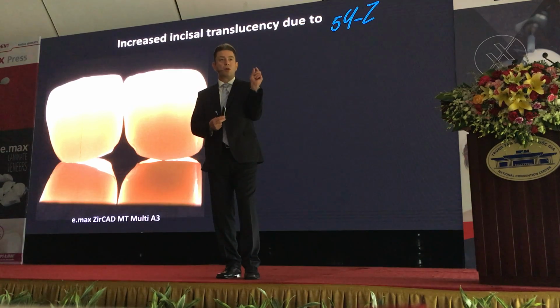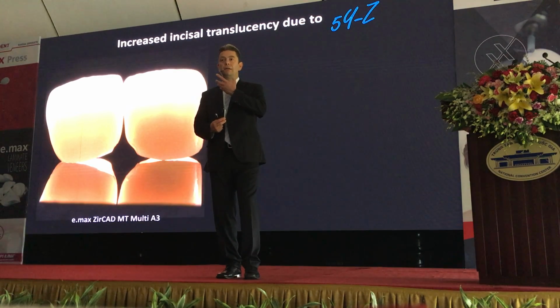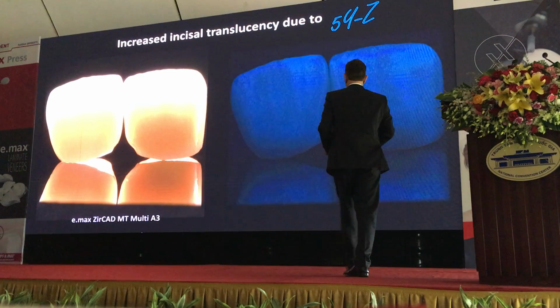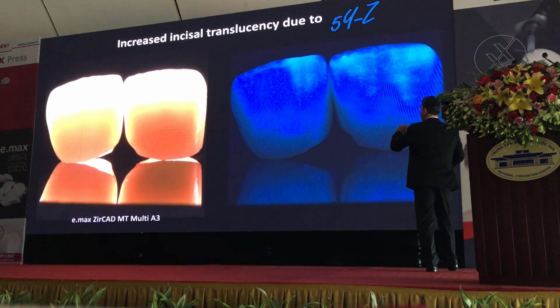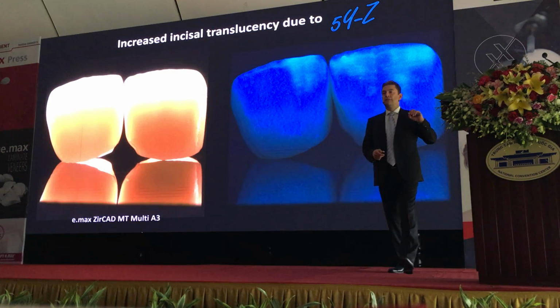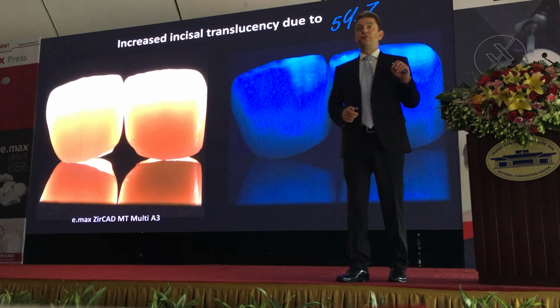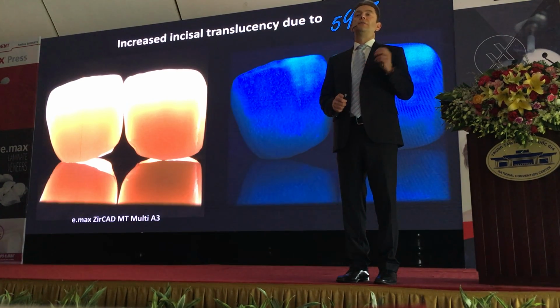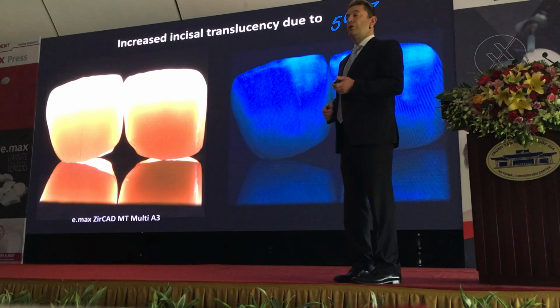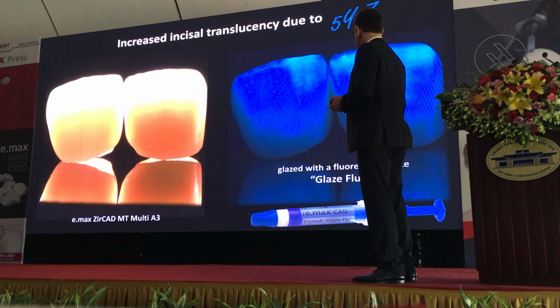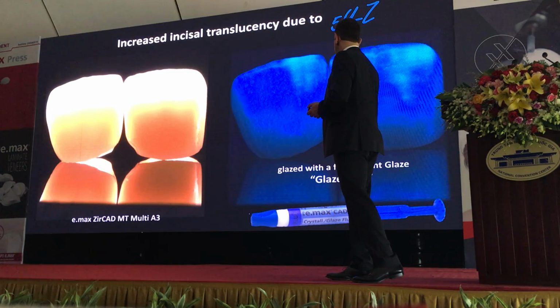So we have more opacity, more chroma and color in the cervical area and more translucency in the incisal edge. And you can see when we expose the restorations to ultraviolet light, usually zirconia is not fluorescent. It's one of the disadvantages of zirconia that it is usually not fluorescent. But what we can do is use a special glaze. This is a glaze that we can apply on top of these zirconia crowns, and this glaze is fluorescent. It's called glaze fluo. So that makes it fluorescent.